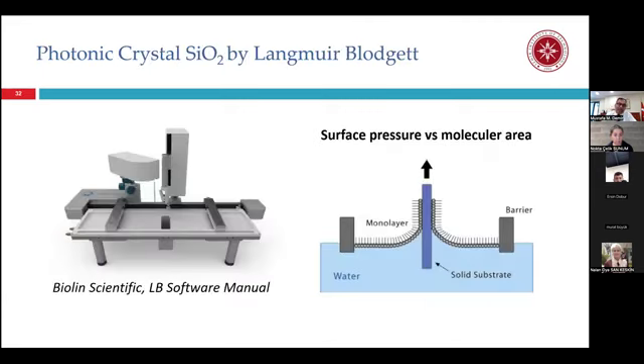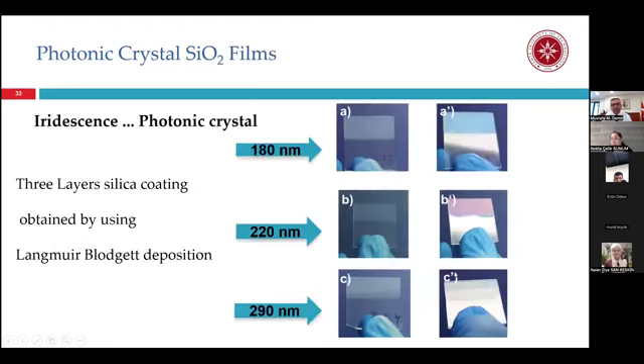So this was a sample prepared by the spraying method. We have a Langmuir-Blodgett system in our lab. In the LB system, you have a substrate. You put the substrate in a colloidal solution. Then you release it back quite slowly, such that colloidal particles are packed on the front and back side of your substrate. So we use a glass slide for various sizes of silica particles, 180, 220 and 290.